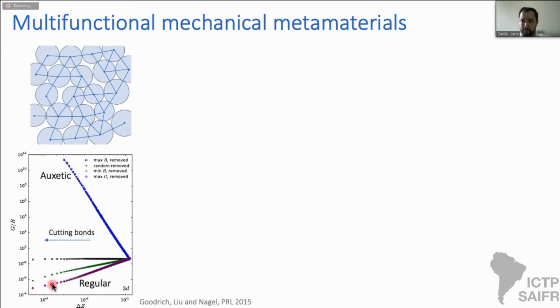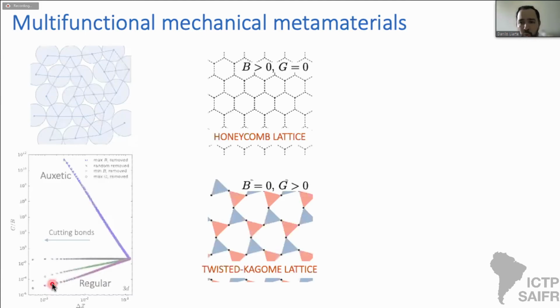Now, we know of two-dimensional isotropic lattices that lie exactly at the limiting boundary for each behavior: the honeycomb lattice that has G over B equals 0, and the auxetic twisted Kagome lattice that has G over B equals infinity. Now, if I can find a way of combining these two lattices, I can design protocols, which for us is just what kind of bonds I'm going to cut out, and then tune the mechanical response in any possible way in 2 dimensions.